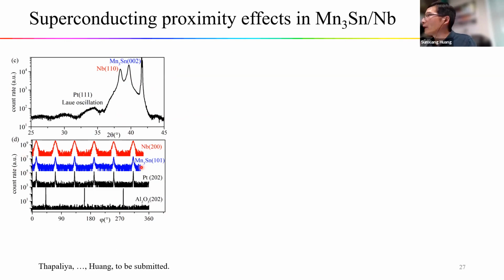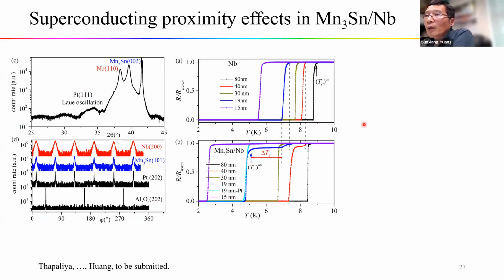Shown here, the in-plane phi scan shows the niobium grows quasi-epitaxially on the manganese-tin, with a relatively broad peak. One characteristic feature of the proximity effect is the suppression of the superconducting transition. We also made a control sample, and we first look at the superconducting transition for the single layer and the bilayer structures. Clearly, the bilayer has a lower transition temperature than the single layer with the same thickness, and the difference increases as the niobium thickness decreases.